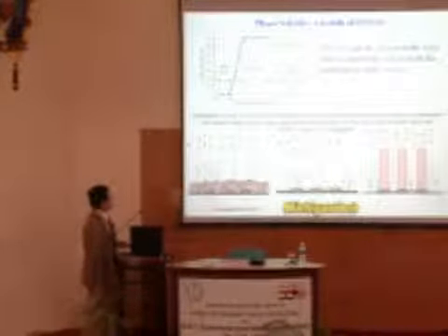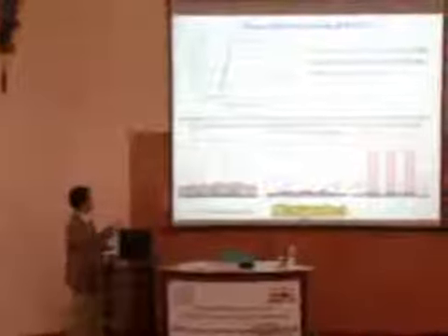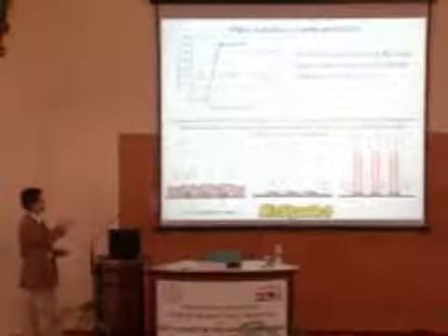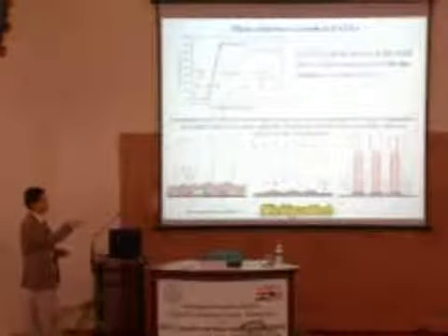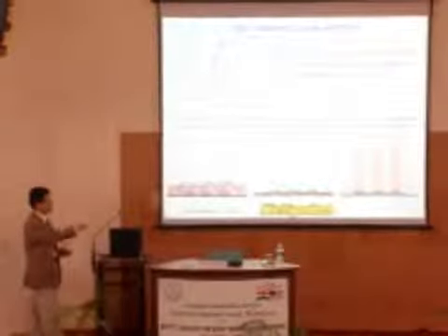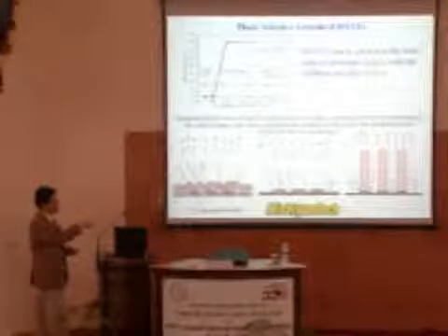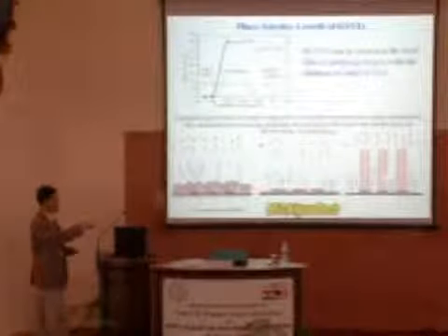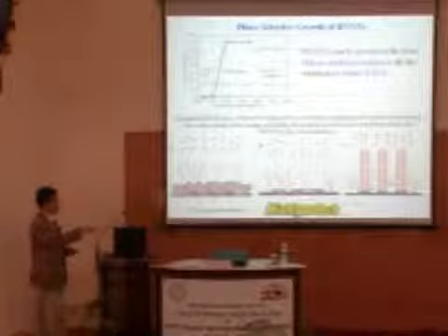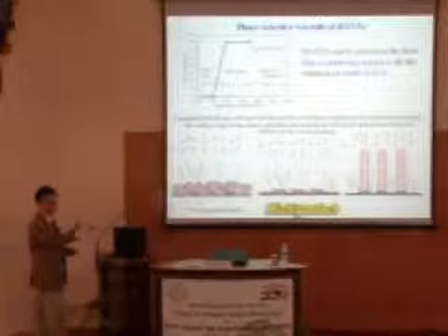Let me skip this one. As I told you, if you apply low bias voltage, you will create boron nitride films. If you apply high enough bias voltage, you have very thin films. If this is too high, most of the atoms will just bounce back, except those absorbed inside the catalyst here, which will allow the growth of the tubes.